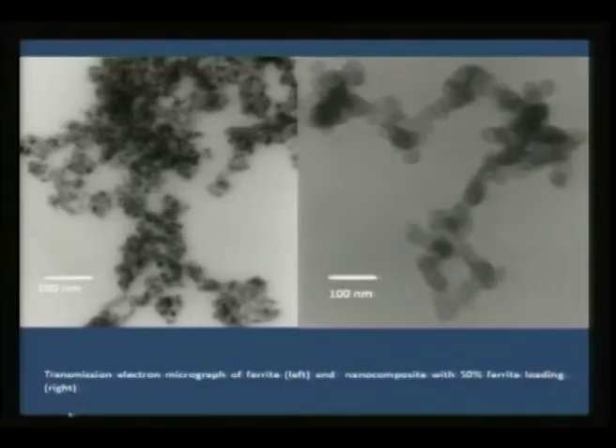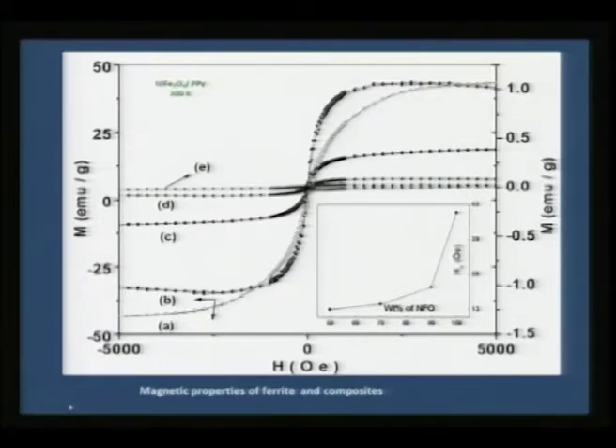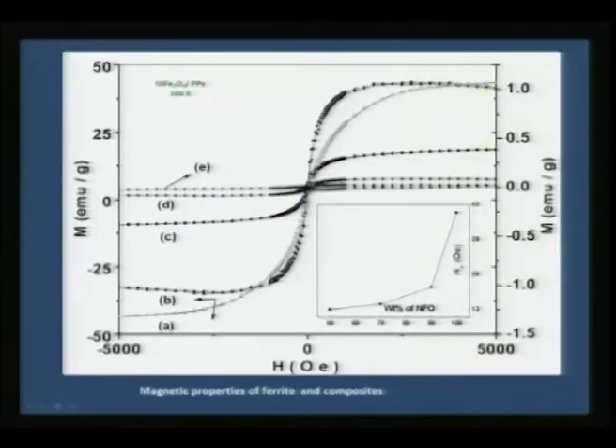In the next slide you can see the X-ray pattern, TEM pattern of this nickel ferrite. This I have already shown, the as prepared one, and how the ferrite loading alters the particle size of this composite, and the magnetic property shows a very clear systematic change with the increasing loading of nickel ferrite. You can see the magnetic signal is changing, and a very clear loop is seen in the middle, typically indicating these are soft magnets.